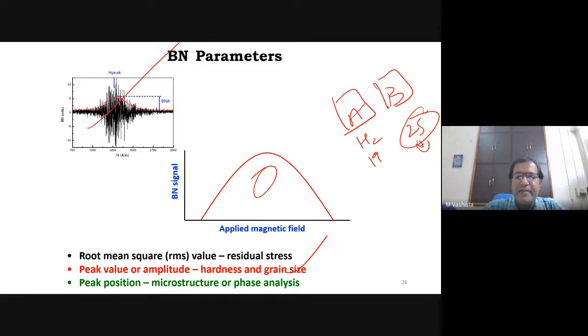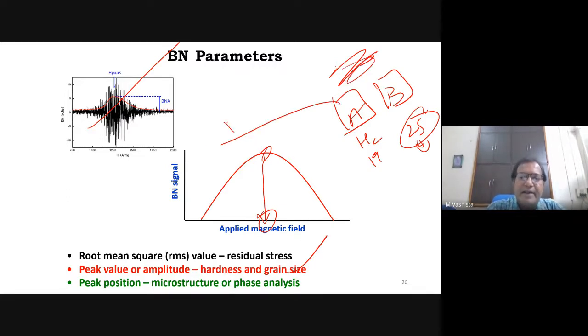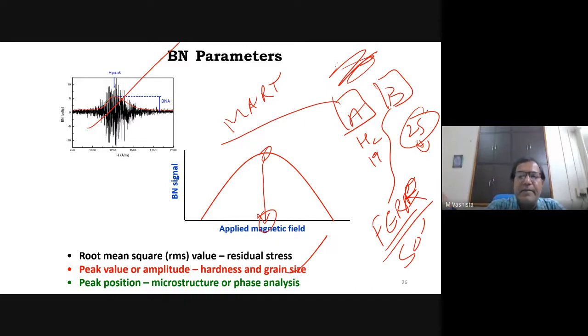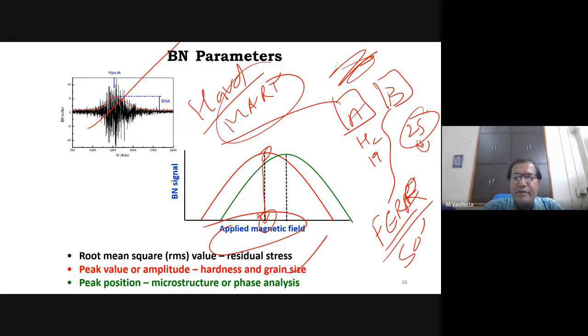Similarly, peak position means the position of this peak on the x-axis. This will indicate the input. The applied magnetic field is the input. So if I have two materials A and B, one has a martensite structure and the other has a ferrite structure. Suppose, okay, ferrite structure means soft magnetic and martensite means hard magnetic. So if the material is hard magnetic, it will require more input. Okay, so if I get the envelope from A and B, what will happen? Martensite will produce this type of envelope. So by getting the information from the shift in peak position, I can identify the microstructure also. So with the help of this technique, we can identify microstructure, and we can identify micro hardness also.